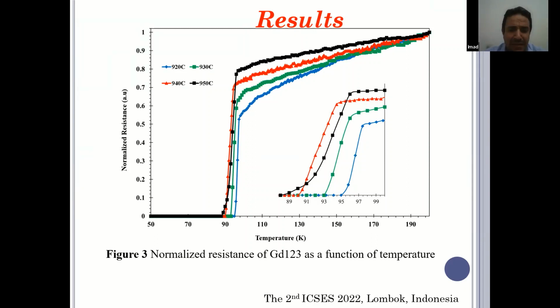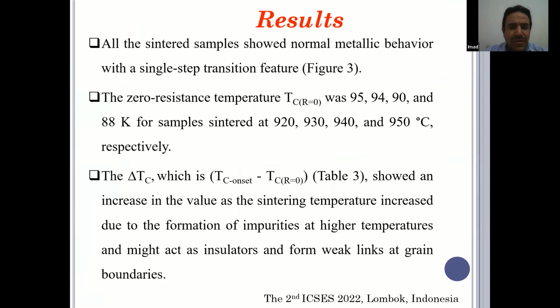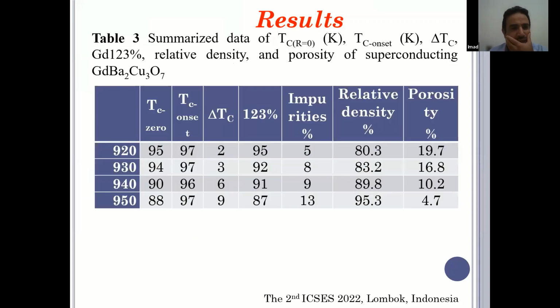For the electrical behavior, all the materials showed metallic behavior, and there is a sharp drop to zero resistance at temperatures ranging between 88 or 89 and 95 Kelvin. Based on that, we saw that as the sintering temperature increases, the critical temperature decreases. All this is found in table 3.